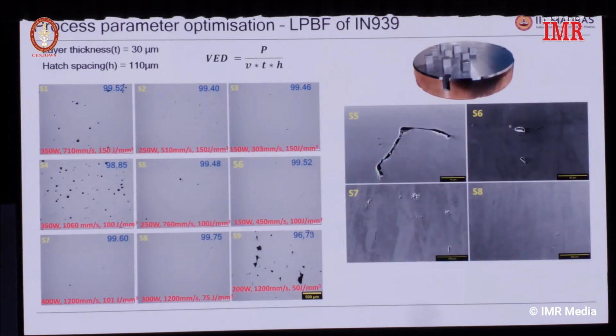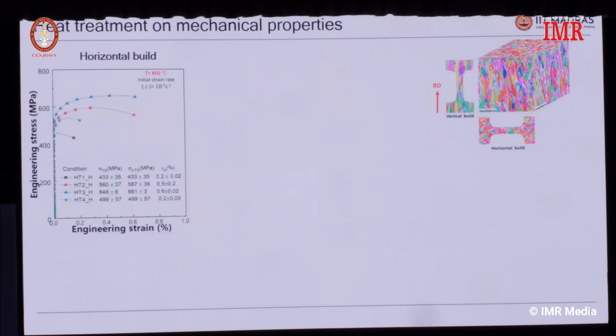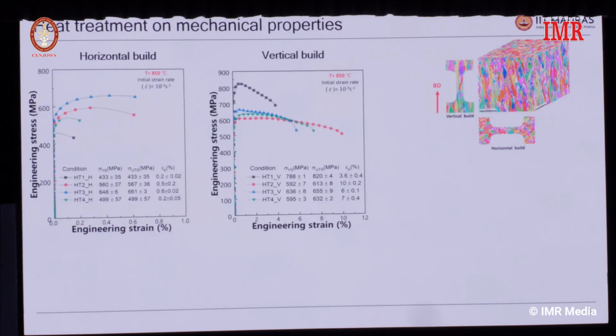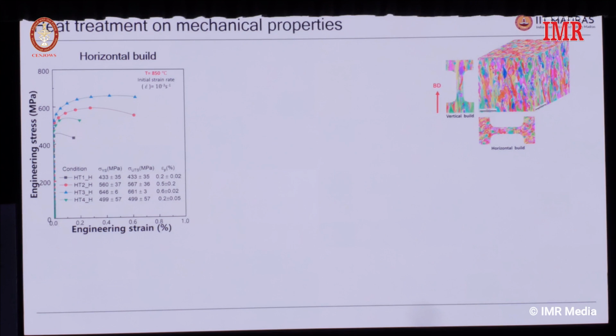Typically, we choose the laser or additive manufacturing parameters of layer thickness, hatch spacing and laser power all together, and we have optimized them. S8 gives a better microstructure compared to all the other parameters. So now we have taken that and done heat treatment, with 4 different kinds of heat treatment.